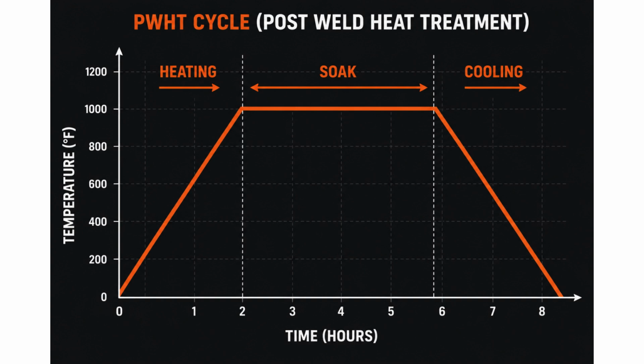This is what actually relieves residual stress and tempers the weld's hardened zone. And cooling, also rate limited above 800 degrees Fahrenheit, typically in a closed furnace, before finishing in still air below that point. Uniformity matters throughout, no more than about 150 degrees Fahrenheit difference across the section being heated.